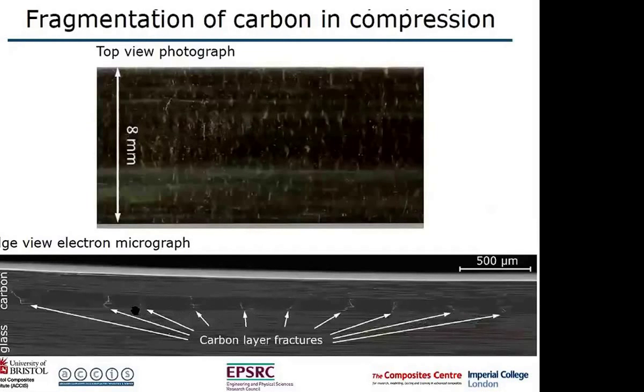And on the bottom here, you can see the surface applied when it's under load. This is about 1.2% strain. You can see these fragmentation events periodically along the length of the carbon ply. We're getting the same sort of fragmentation in the carbon, even when it's loaded in compression. The pitch of these fragments is quite close.